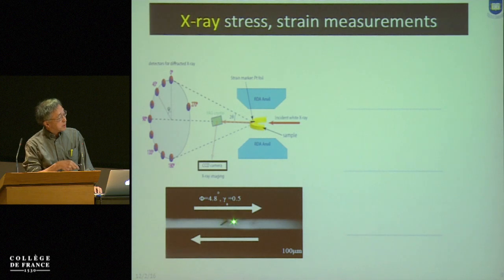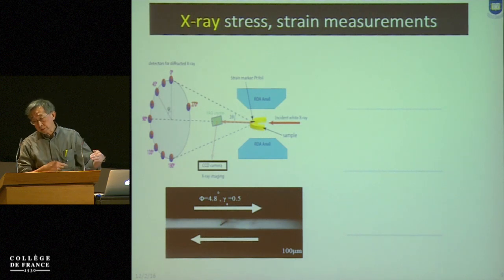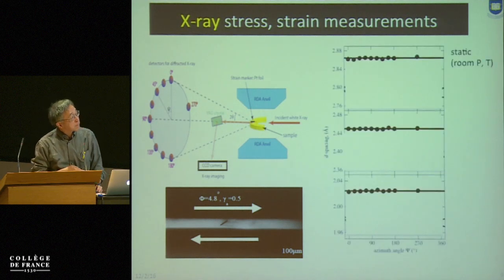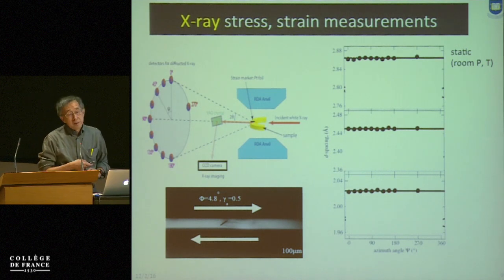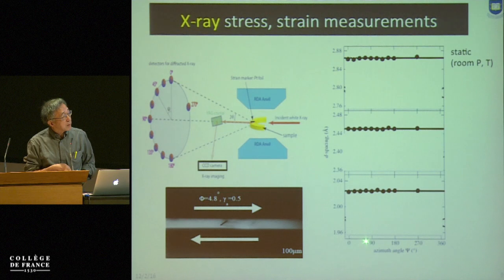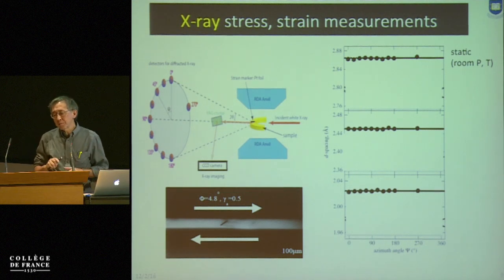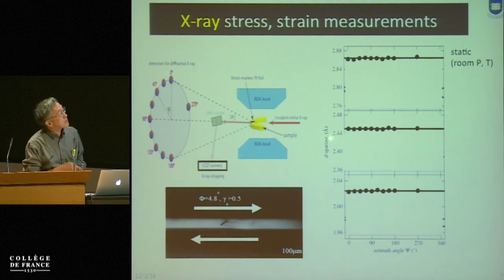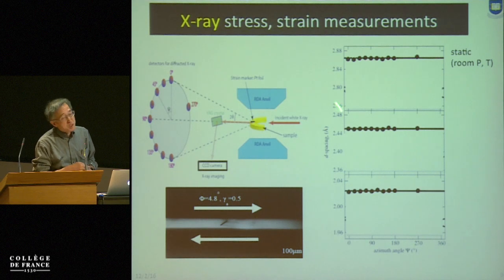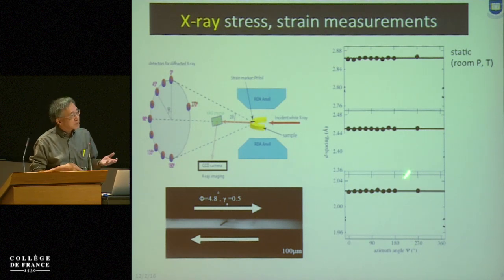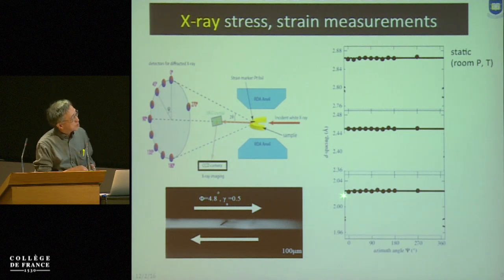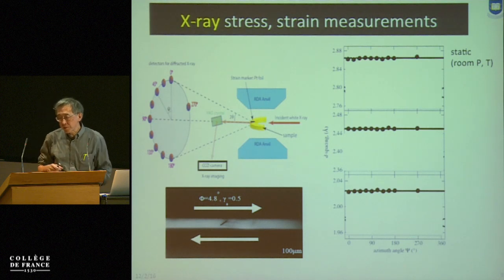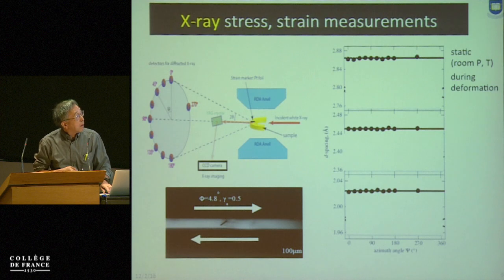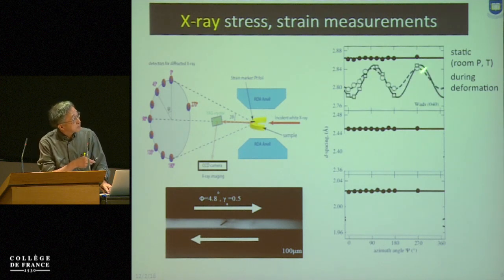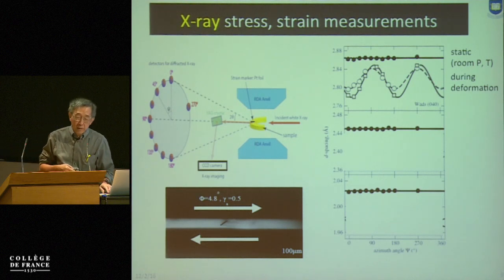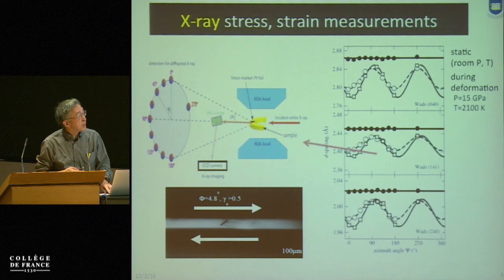And this is the strain measurement. You have a specimen, and you can see the marker. And then from the rotation of the marker, you can determine strain rate. And by X-ray diffraction, you can determine stress. If you take X-ray diffraction as a function of various angles before you apply the rotation, lattice spacing is constant at all angles, and whatever orientation you measure, it is always the same thing, like 2.02 angstrom. However, when you start rotation, symmetry is broken, and the lattice strain changes sinusoidally with orientation, from which you can estimate stress.